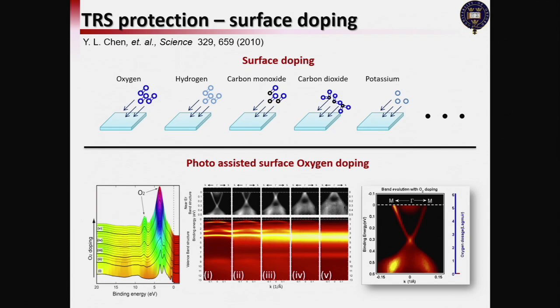I will use oxygen as an example. Oxygen goes onto the surface and oxidizes the surface. What will happen? You see that the oxygen indeed went to the surface because the oxygen peak grows from nothing. This is the band structure, and this part is a zoom of the 0 to 0.5 eV region to clearly see the surface state. We see that the bulk state was gradually smeared out, but the surface state remains. However, the chemical potential goes down. That means the oxygen is sucking out all the electrons. That's normal.